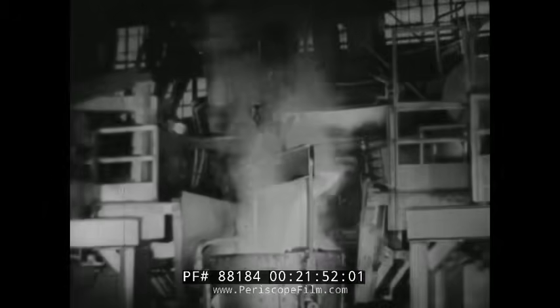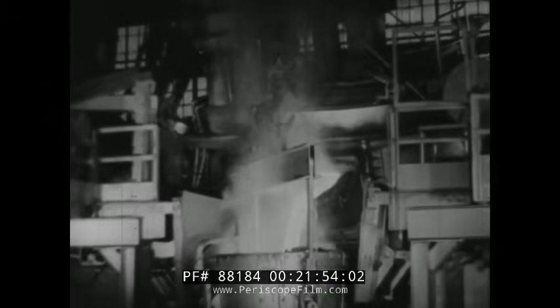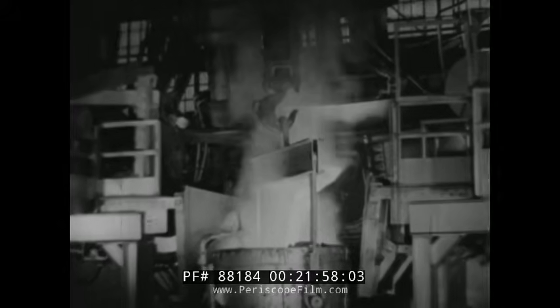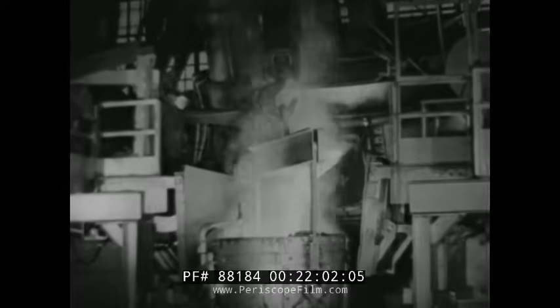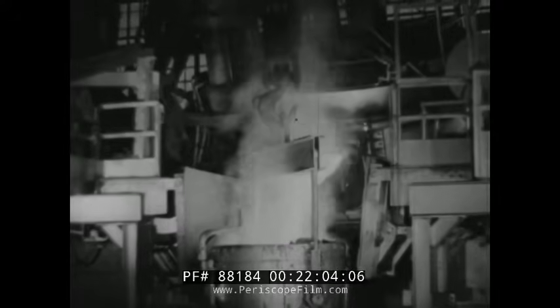The pouring of an electric furnace heat is a spectacular sight. A crane brings up a heavy ladle to receive the molten metal and holds that ladle under the pouring spout. A tilting mechanism tips the furnace so that the metal pours out of the spout into the ladle. As the furnace tilts further, the crane lowers the ladle until finally the furnace is empty.